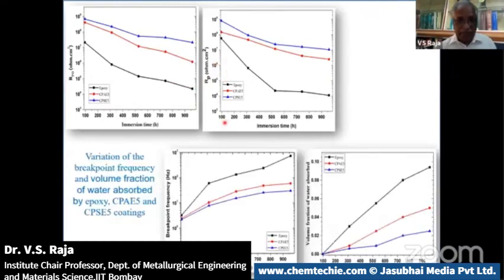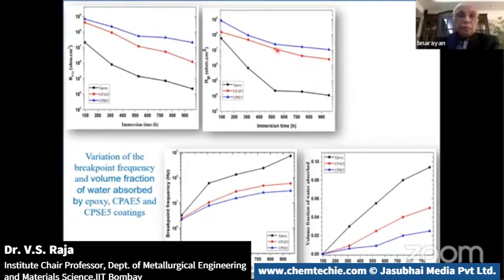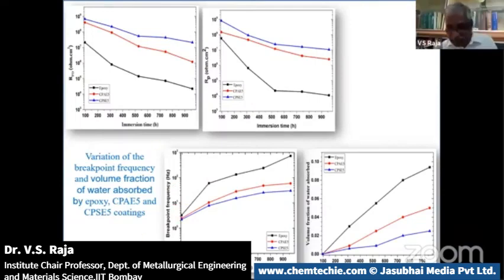What you see here is the resistance of this coating versus the immersion time. You can see this 10 power 9. The decay is not that sharp. And in the neat epoxy, you can see that there's a sharp decay in terms of resistance. So the modification of this molecule with these additives has given rise to a significant improvement in the corrosion performance of the epoxy. There is something called breakpoint frequency, which is too much science, so I will not dwell on it, but these are some of the techniques which are useful to really understand the coating properties without taking thickness into consideration.